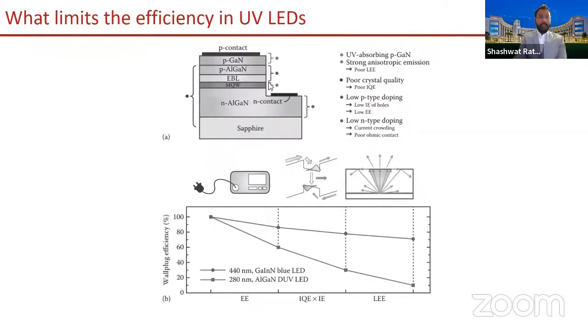So what really limits the efficiency of these LEDs, right? There are many elements. I'll break it up quickly to the important ones that we are working on. One is that you have defects in the material in this quantum well where you generate the light. You have these point defects that essentially trap your carriers, and they do not let them recombine to emit light. So because of poor crystal quality, essentially poor quality of the material, you lose out on a lot of efficiency because of this.